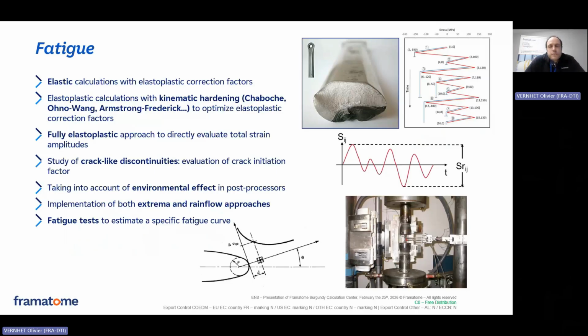Then another failure mode that we study a lot is fatigue, also with cyclic loading. Once again, it's codified in different codes, RCCM and ASME, with elastic approaches. So we begin with these approaches. If it's not suitable, then we use elastoplastic approaches, also with kinematic hardening, the same kind of model I spoke about. If optimizing the elastoplastic correction factor is not enough, then we might use a full elastoplastic approach where we calculate total strain amplitudes directly, to implement them directly in the Miner accumulation.